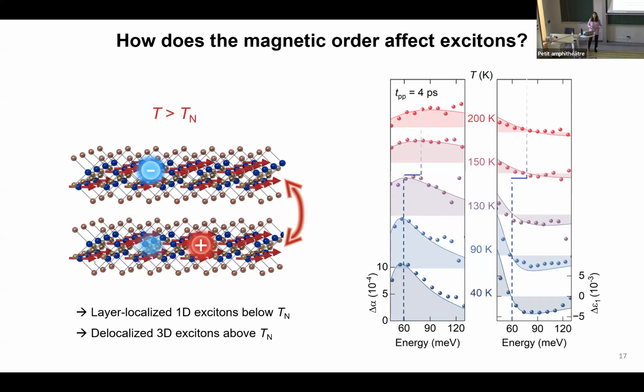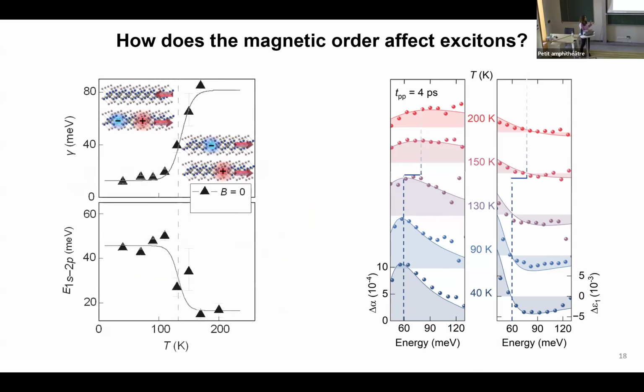So we literally start delocalizing the electron and hole pairs across the space. It is as if they start to acquire a more three-dimensional like behavior. And this delocalization generates a lot of scattering phenomena that broadens the spectrum. And we all know that in a Lorentz function or a damped oscillator, when the broadening overcomes the center energy, we start to see an artificial blue shift in our energy spectrum. In order to theoretically reproduce this data, we have to take into account the simultaneous effect of the change in the binding energy of the electron and hole pairs together with the broadening factor.